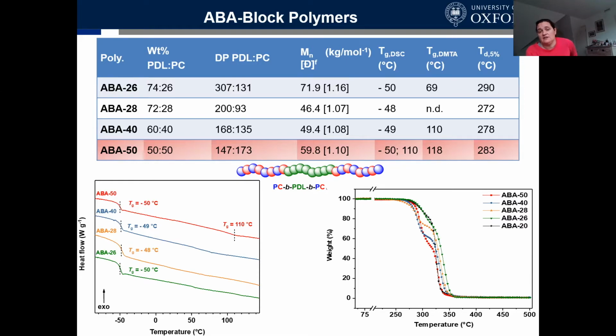And we have studied its phase-separated nanostructure, and it is in the regime of thermal and phase-separated properties where we'd expect it to be a plastic. So here you can see some DSC data showing you that the blocks are phase-separated. So you have 2 glass transition temperatures, one around -50 for the green portion of the polymer, one up about 110 for the rigid polycarbonate portion.